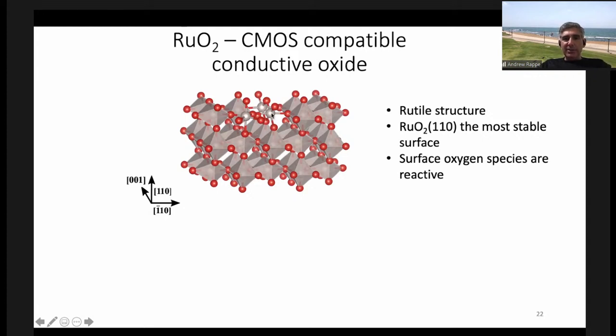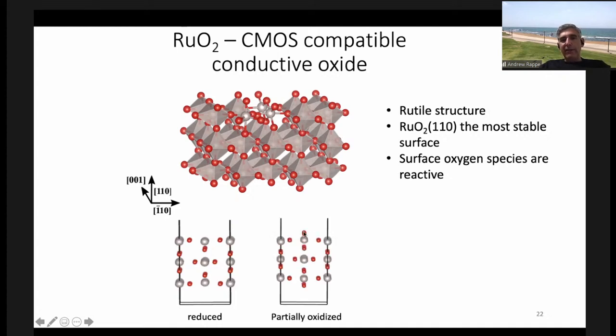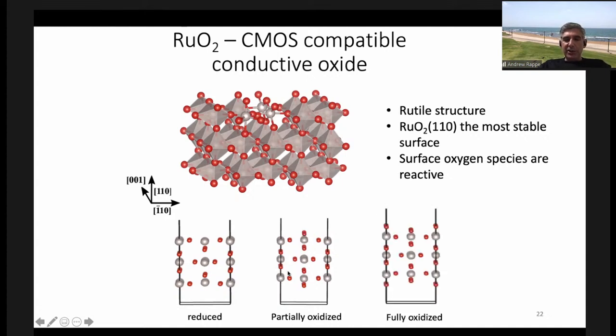Okay, so the ruthenium are these gray spheres, and the oxygens are these red spheres. And it turns out the surface oxygen is reactive. So there's three possible surfaces. You could have ruthenium oxide layer with no oxygen on top, with half the sites having an oxygen, or with all the sites having an oxygen. So we call that reduced, partially oxidized, and fully oxidized. And for a while in this project, we carry through with all three of these possible scenarios, and you'll see why.